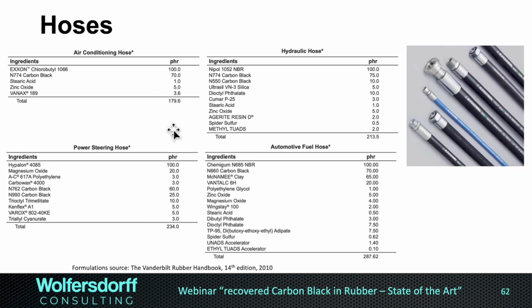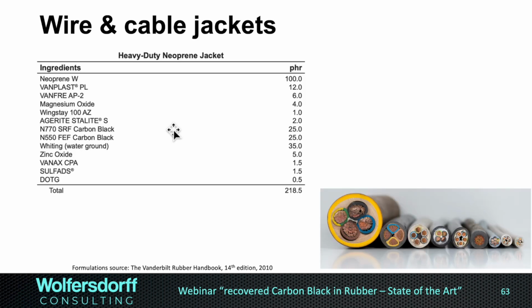Hoses, there's really a lot of hose formulations in the Vanderbilt rubber book. So air conditioning hose, hydraulic hose, power steering, automotive fuel hoses. They're all featuring the 3 big groups of semi-reinforcing carbon blacks, the 700, 600, and 500. And the more we have 700 and 600, the easier it is for the recovered carbon black to replace. The 550, as a higher structure carbon black, is a little bit more difficult to replace with recovered carbon black.